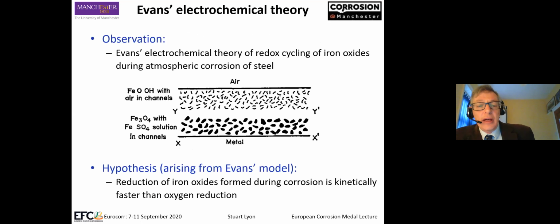Going on from atmospheric corrosion of steel, Evans' electrochemical theory was based on the redox cycling of iron oxides during atmospheric corrosion. And again, a hypothesis arising from the Evans model is that the reduction of iron oxides formed during corrosion is kinetically faster than the oxygen reduction reaction. And again, we check that.